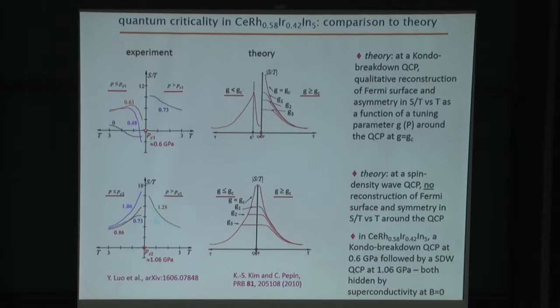So we can compare these experiments to theoretical predictions, and this is why I hoped that Catherine would have been here today, among other things. So we're comparing to a theory of Catherine Pépin, who has calculated the thermal power as a function of a tuning parameter, in her case g, where she can now plot the temperature dependence of this thermal power divided by temperature for different values of a tuning parameter. In our case, this tuning parameter is just pressure.